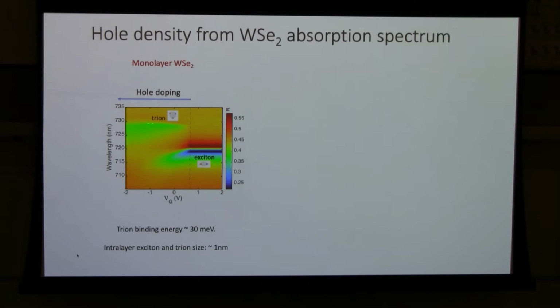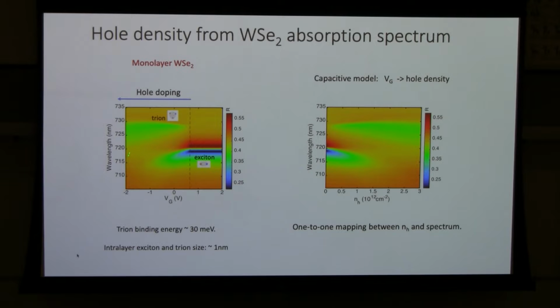Because the optical spectrum changes very strongly with hole doping, we can map the optical spectrum to the hole doping one-to-one. For this system, we only have a gated two-dimensional hole gas, which is very well understood. As a result, we can map the gate voltage into hole density using a capacitive model. Once we do that, we can convert this gate voltage versus spectrum into hole doping versus spectrum. So the spectrum has a one-to-one correspondence to the hole density in the system.